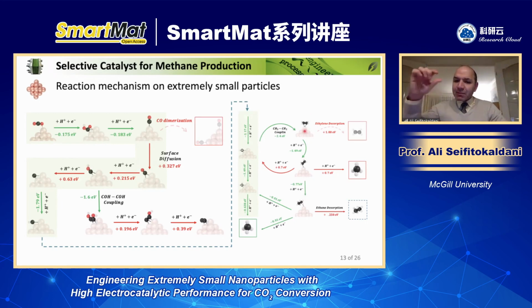But you can again do another hydrogenation. So you can easily expect that as soon as the ethylene adsorbs on the surface, you can convert it to the adsorbed ethane. But then ethane can leave the surface much easier than ethylene. So here the energy barrier to leave the surface was 1 electron volt, which we don't expect to happen easily, even at room temperature. But then for ethane, it was 1/4 of that, like 25% of that, 0.25 electron volt, which is surmountable. And you can expect that even at room temperature.